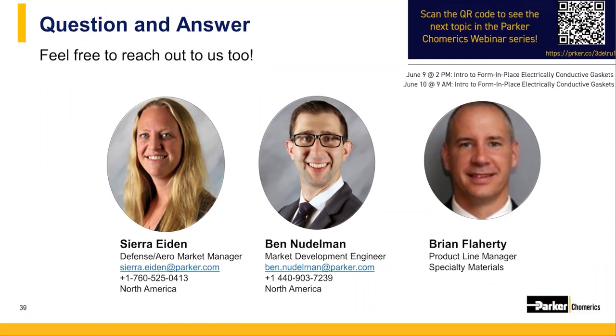Yeah, and I apologize, Ben, this was more like a 3-part question, so I'll just ask Catherine's other 2 questions in a row. So regarding edge flaking concerns during masking removal, are there other recommendations such as specifying time to removal? Yeah, so that's a great question, actually. A lot of people see flaking and cracking of conductive coatings depending on the type of coating, the type of cure schedule that you're using, and the time you take to remove the masking. Typically, if possible, I recommend that you remove the mask when the paint is wet. It's not always easy to do depending on your application, but that will give you the cleanest break.